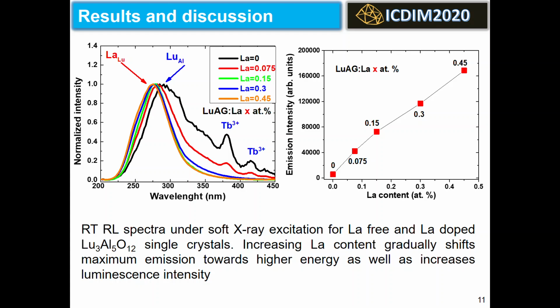Interestingly, the dominant luminescence moves its position gradually from 292 to 275 nanometers with increasing lanthanum content. It should be noticed that luminescence at 292 nanometers in the undoped LuAG belongs to the lutetium-aluminium emission center, whilst the luminescence at 275 nanometers in lanthanum-doped LuAG is ascribed to the lanthanum-lutetium emission center. Moreover, lanthanum doping significantly increased the intensity of ultraviolet luminescence.